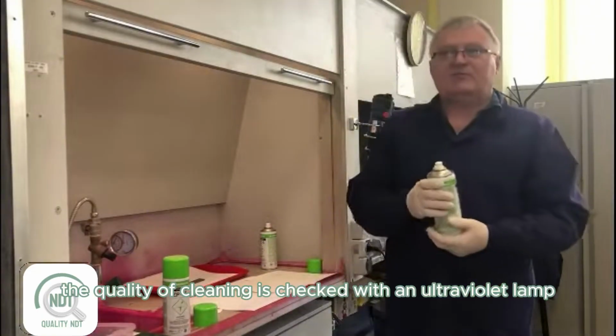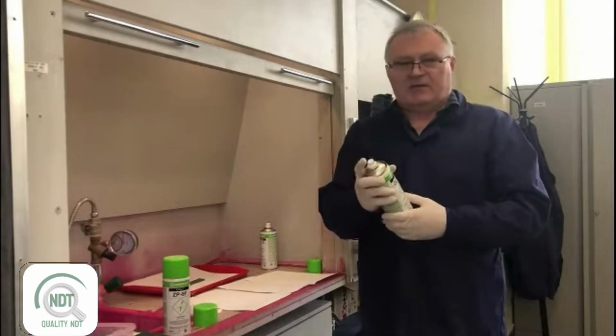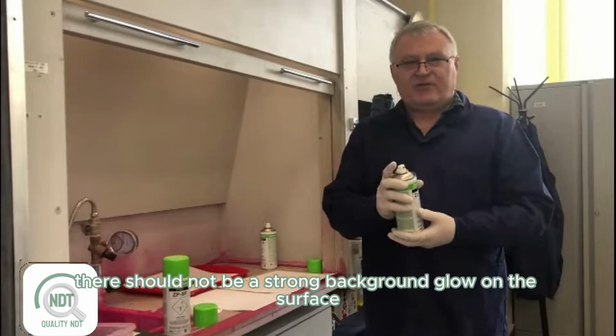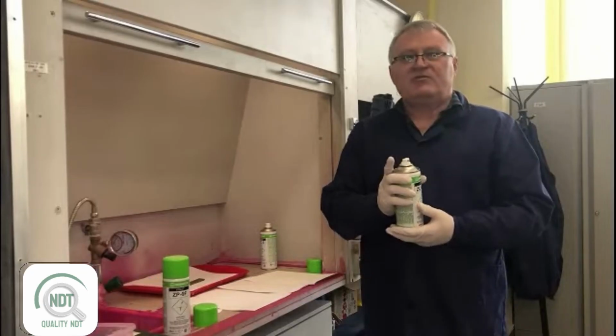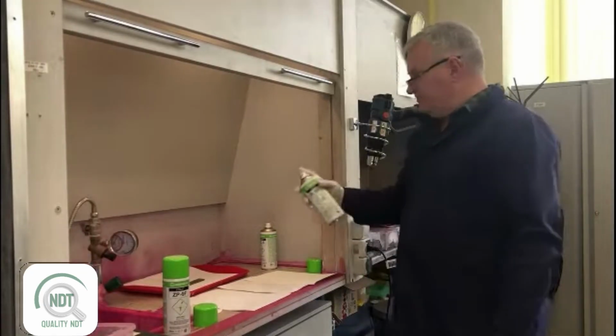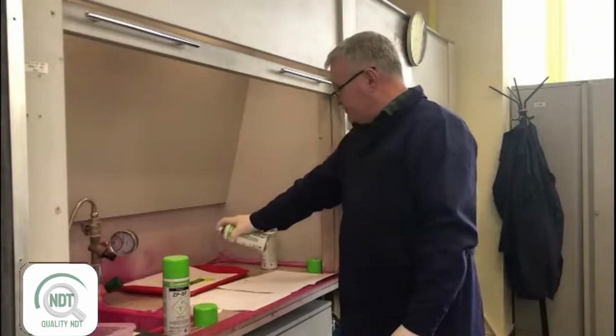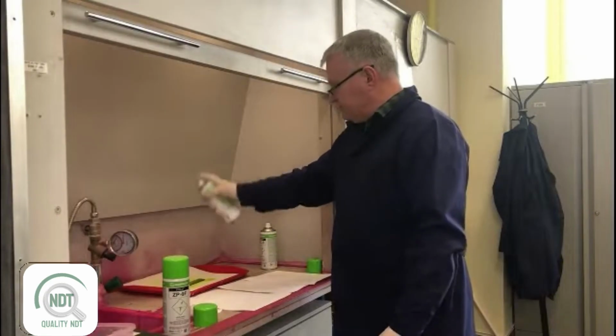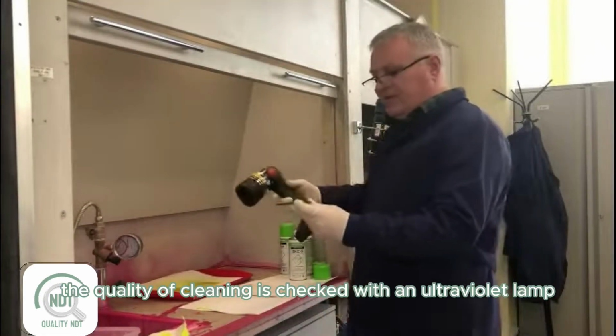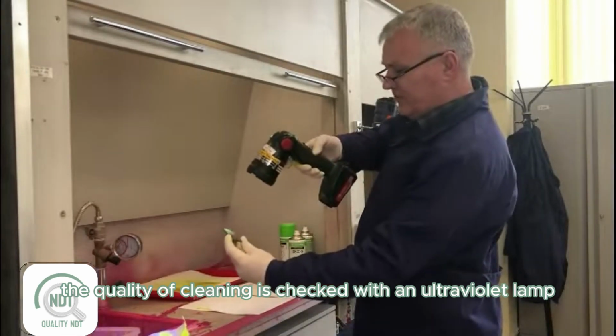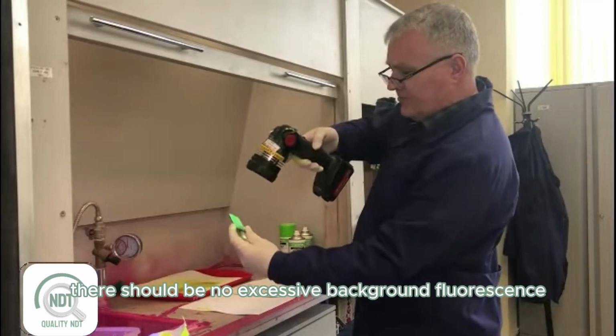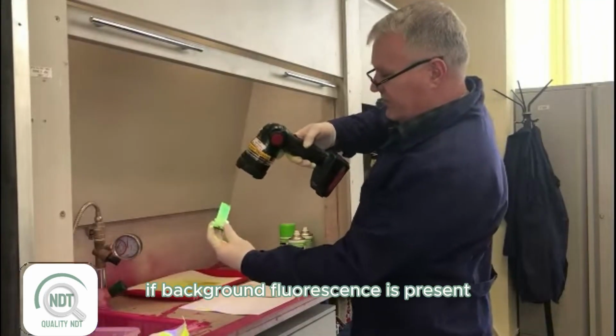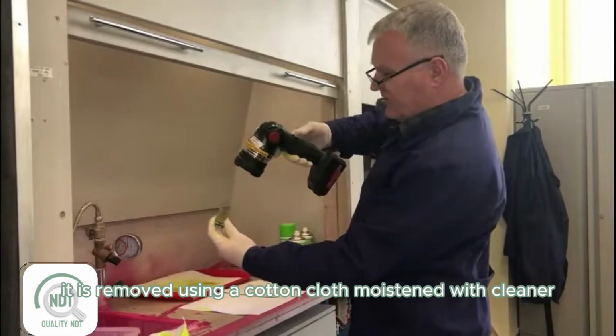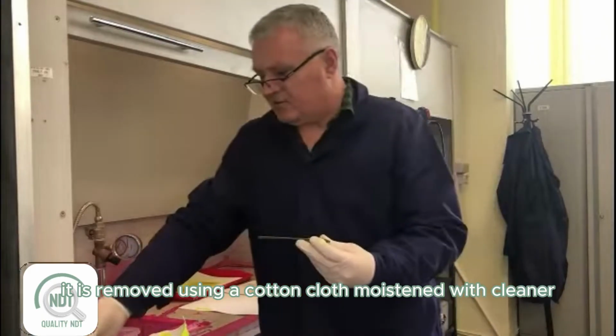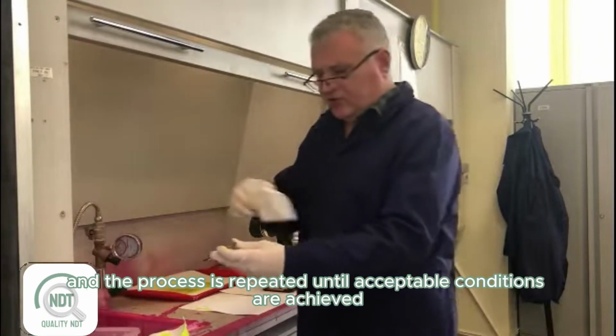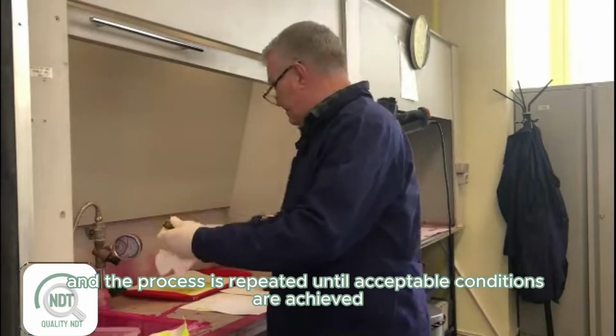The quality of cleaning is checked with an ultraviolet lamp. There should be no excessive background fluorescence. If background fluorescence is present, it is removed using a cotton cloth moistened with cleaner, and the process is repeated until acceptable conditions are achieved.